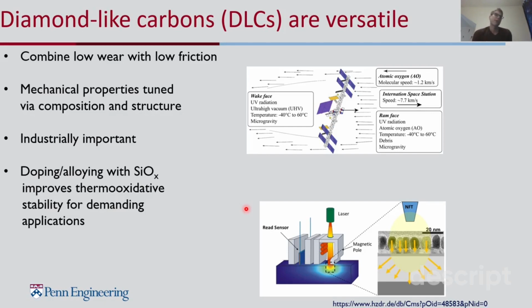And so this makes them attractive for applications like, for instance, solid lubricants in low Earth orbit, where you have a lot of charged particles flying around that tend to erode undoped diamond-like carbons. And then also the hard drive industry is trying to go to a higher density recording technology by using very high temperatures in the storage media. And these storage media have always been protected by hydrogenated amorphous carbon, and it turns out these high temperatures lead to very rapid oxidation. And so by doping the materials with silicon oxide, you can actually reduce that quite a bit and make them a candidate material for this technology.